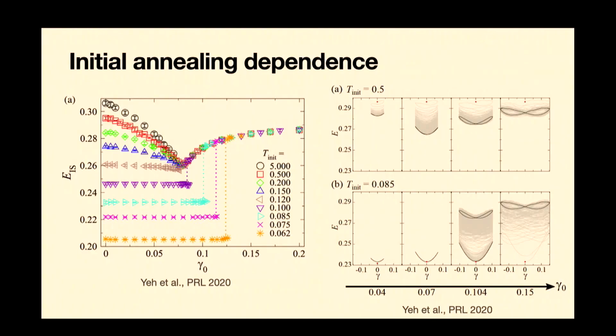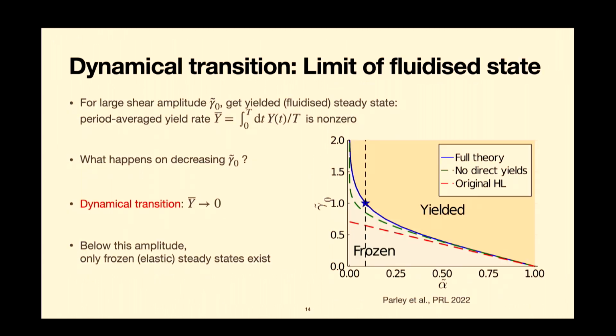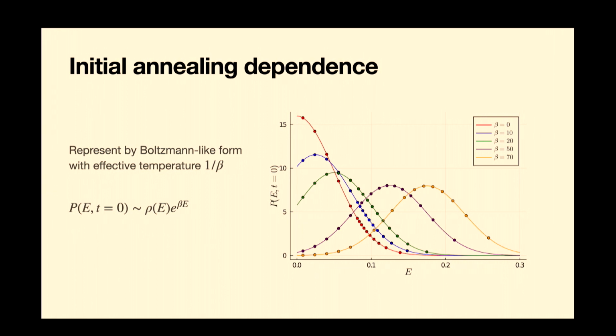One more question. Can you go back to this experimental data? You said that when you go to the well annealed glass regime from the poorly annealed glass, your yield strain systematically moves, and that you do capture in the elastoplastic model. So in the elastoplastic model, what controls the shift in strain? Broadly speaking, it's the way we assume the sample is prepared. Very roughly, you could think of the system as being stable up to strains where you've eliminated a minority of the initial preparation, so you eliminate all the local regions with small yield energies.